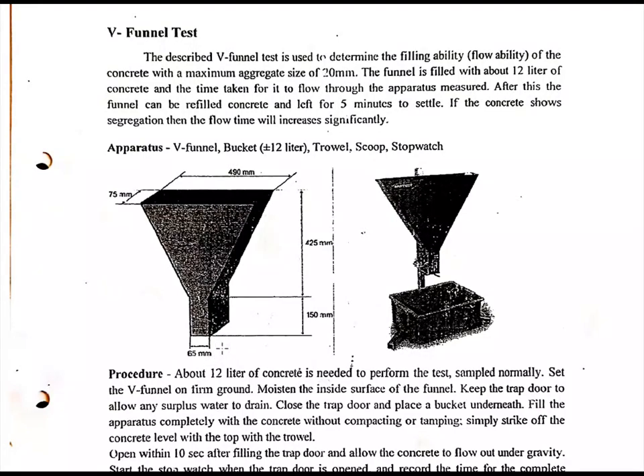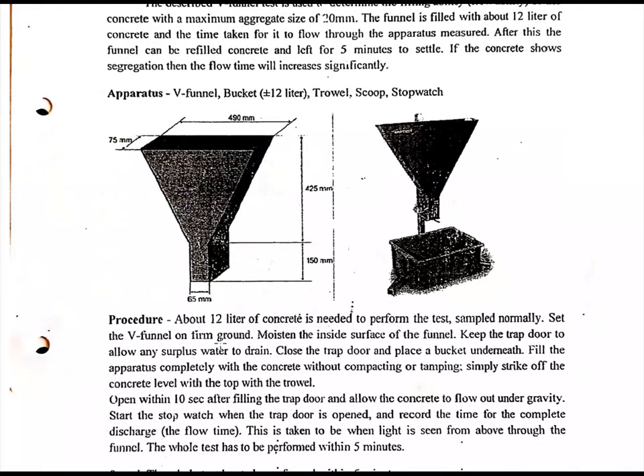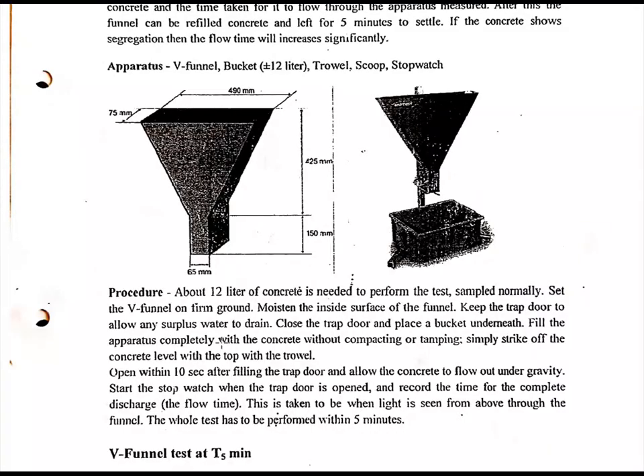At the bottom you will have a trap door. That trap door is closed at the beginning, and you have to grease the inner surface of this V funnel and then fill the concrete. The amount of concrete required here is 12 liters. You put that 12 liters of concrete into the V funnel. After placing, you wait for 10 seconds and then open the trap door. The time taken from the moment you open the trap door until the concrete has completely passed out is noted. The stopwatch must be started the moment the trap door is opened.